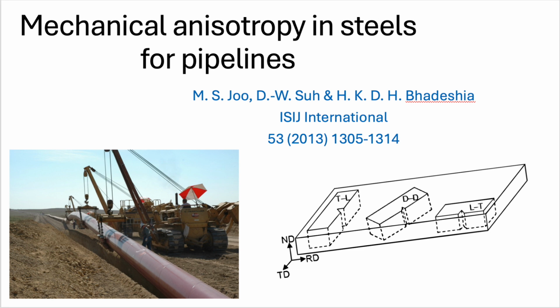So all that effort to get high-strength X80 steel could be undermined if the toughness in that critical hoop direction isn't good enough because of these inherent anisotropy issues. That's the fundamental challenge. The very process of making the strong plate introduces directional weaknesses that line up perfectly with the service stresses in some common pipe designs. We've seen why that toughness isn't uniform. It's down to these three culprits: inclusions, banding, and texture. It really highlights this constant balancing act in material science, pushing for higher performance, like strength, but always battling these more subtle, inherent limitations, like anisotropy.